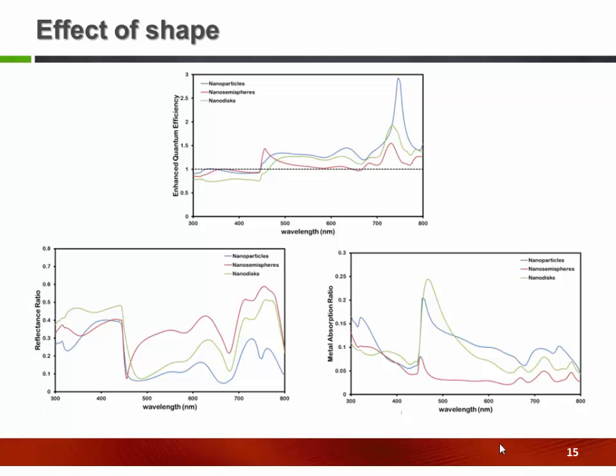But at the same time, I would like to highlight the metallic absorption. As we see, the lowest metallic absorption happens in the semi-sphere compared to the sphere or the nanodisk shaped material. So if we are looking for a structure, for example for my application, which is some sort of transparency, semi-sphere shows the best application. But at the same time, reflectivity is also another parameter, which shows that semi-sphere has higher reflectivity. These are some tips that show me that the application I want to use this structure on top of is maybe not very good for the semi-transparent cell. But for overall enhancement, they are definitely going to improve performance.